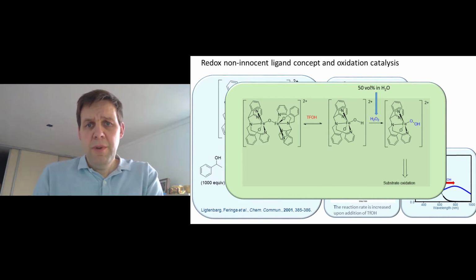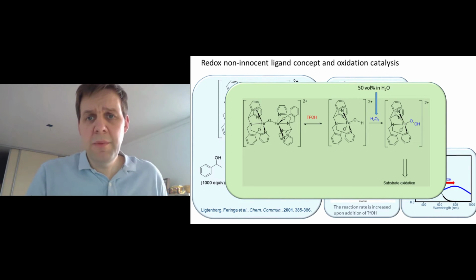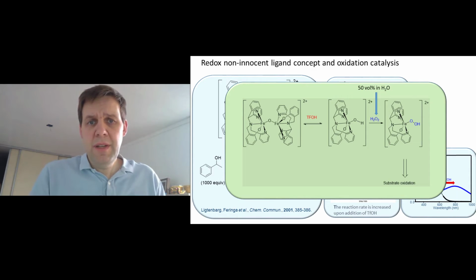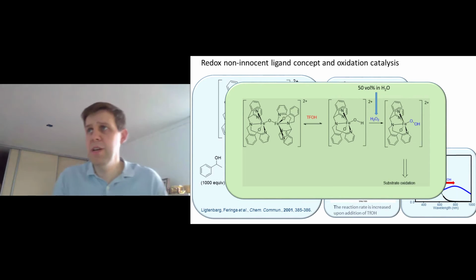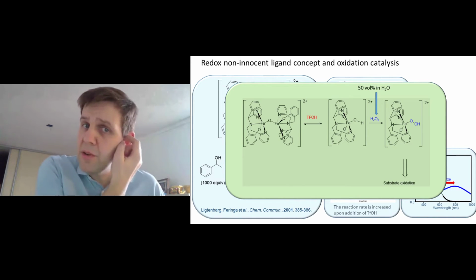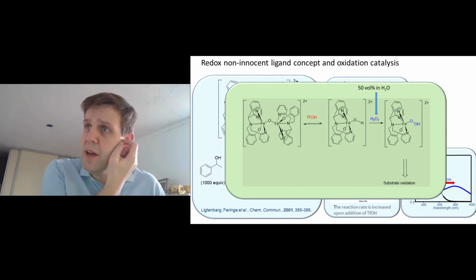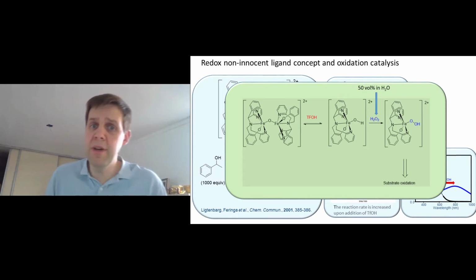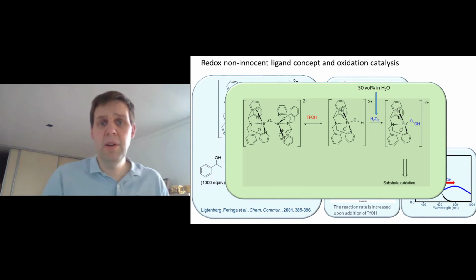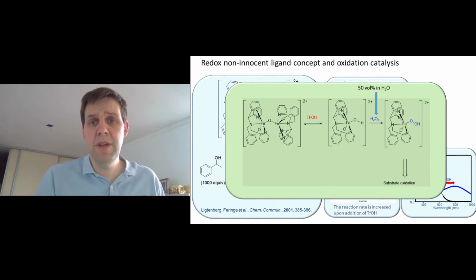One problem is that if we add hydrogen peroxide, it's 50% volume in water at the maximum. And that means a lot of water is added to the reaction. And water has an effect on triflic acid because triflic acid is a very strong acid. But if water is present in acetonitrile, you have the leveling effect. And then the strongest acid you can have is a hydronium ion. And that actually shifts the equilibrium back to the original compound straight after the hydrogen peroxide is added. And then the rest of the reaction continues under relatively non-acidic conditions.